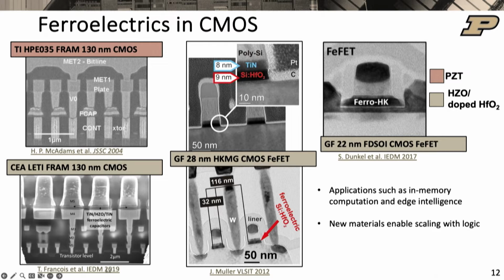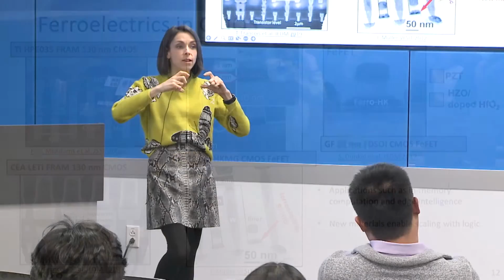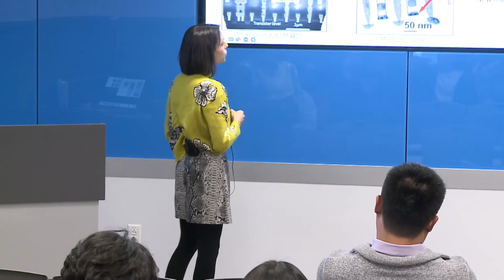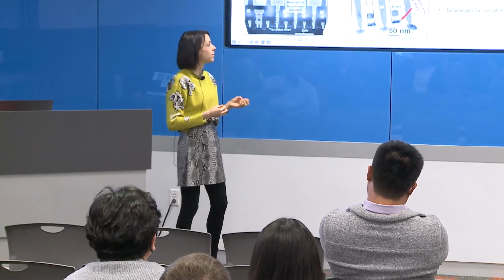But like I said, people really looked a lot at integrating ferroelectrics into the front end of line. And so you can see all this literature, and we know all this development to product and close to launch for ferroelectric films in CMOS front end, which is very exciting because remember that transistor sensing I mentioned and how that gate dielectric gives you the field effect. Well, imagine if that field effect is actually from a ferroelectric, which is going to give you a much stronger response, and it's amplified by the transistor transconductance. Right? So then you get this beautiful boost in performance by at least 1,000x.